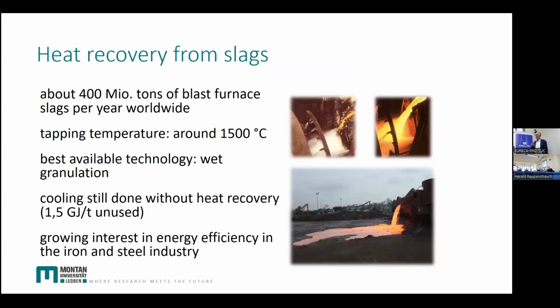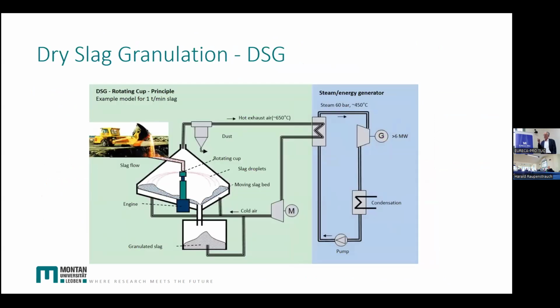So why is this cooling important? It's not only for the slags we are talking about. The cooling of slag is a principal worldwide problem. About 400 million tons of blast furnace slags per year are cooled down with water. That means about 1.5 gigajoule per ton of energy is unused. So if you can granulate it, cool it down really fast, not with water but with air, this is one possible principle. You heat up the air, and this hot air, in this case with a temperature of about 650 degrees centigrade, can be used for producing steam and electricity, or what else.